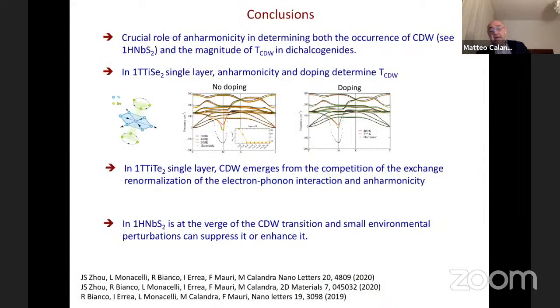So let me conclude. I told you practically everything I wanted to tell you. There is one important point that has to be considered, and the important point is that anharmonicity is crucial in the theory of charge density waves, and the old theory of Peierls, in which you simply consider the energy gain by the distortion as due to the band gap opening, is completely incorrect in these systems, because you always have the interplay between three different effects: the electron-phonon interaction, the effect of the electron-electron interaction on the electron-phonon coupling, and most importantly, the anharmonic effect.